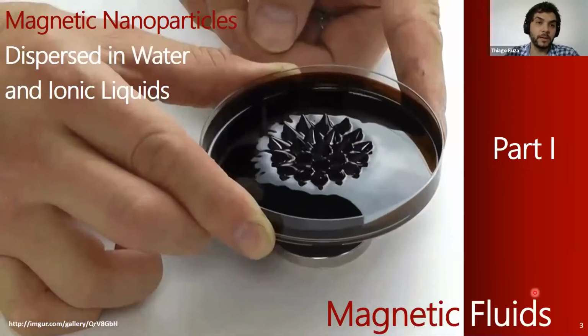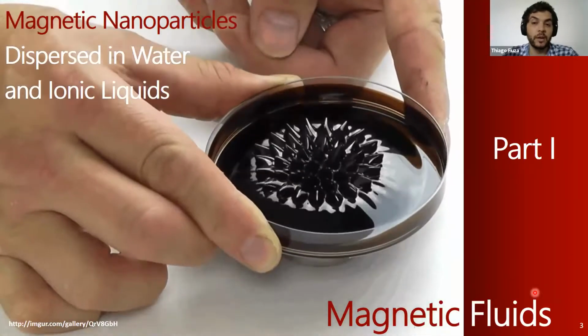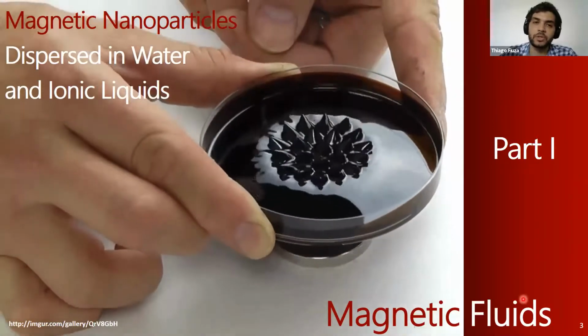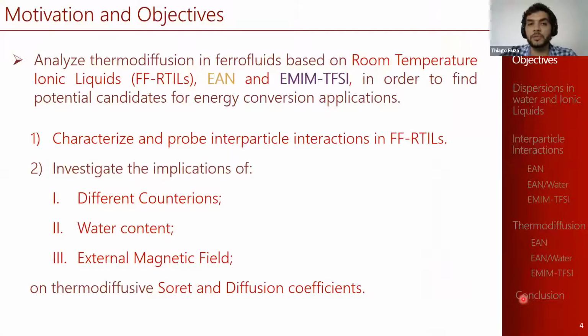So first, I would like to talk about the magnetic nanoparticles alone, the magnetic fluids. Our motivation here is to analyze the thermal diffusion in room temperature ionic liquids, ethyl ammonium nitrate and EMIM-TFSI, in order to find potential candidates for energy conversion applications. The first step we do here is a characterization in which we probe the interparticle interactions. Then we investigate the implications of the different counterions, the water content, and the application of an external magnetic field on the thermodiffusive coefficients, the Soret and the diffusion coefficient. In the next sections, you can follow which sample I'm talking about here on your right.